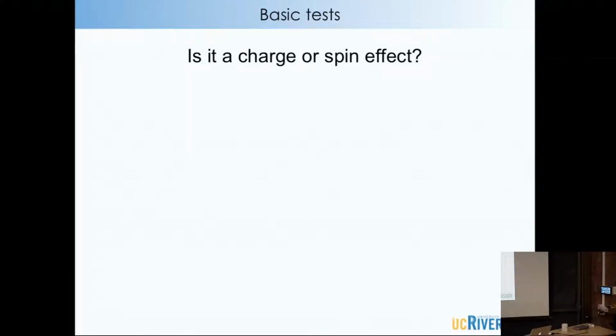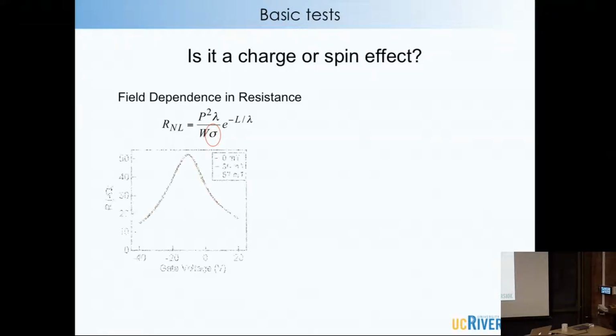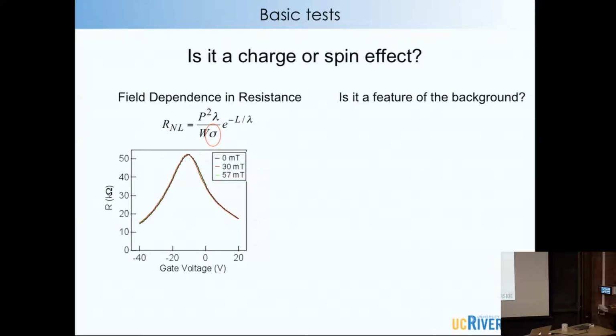Okay, so we want to do basic, actually most of the experiment was control experiments. I'll just show you a couple of them. So first of all, is it a charge or a spin effect? Because if you look at the theory of what the signal should look like, there's not just the spin diffusion lengths in there, but there's also conductivity. So if the conductivity is changing, then you're going to generate a dip, and has nothing to do with spins, right? So we do a couple of measurements. Here, we looked at the magnetic field dependence, and the conductivity doesn't change, or the resistance doesn't change. And I'll show you a more detailed scan on the next slide.